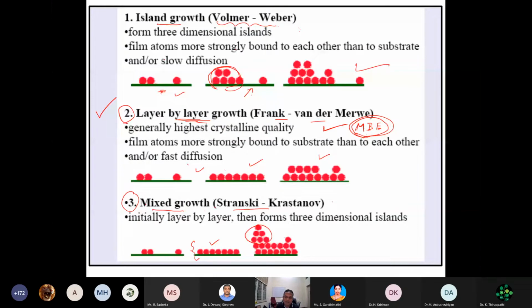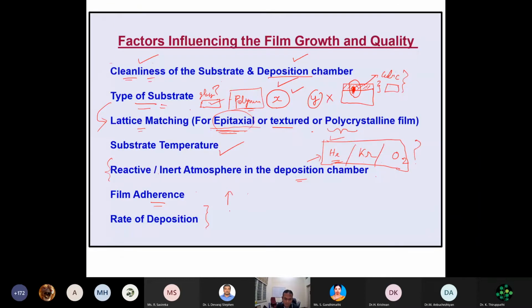So something like island growth mode or mixed growth mode, you will be ending up. If I want to have a layer by layer growth mode, to have an epitaxial film growth, I have to keep my rate of deposition very slow. But of course, it takes long time to deposit. But if you want to have a quality thin film, your rate of deposition should be very low. Okay, that is very, very important.